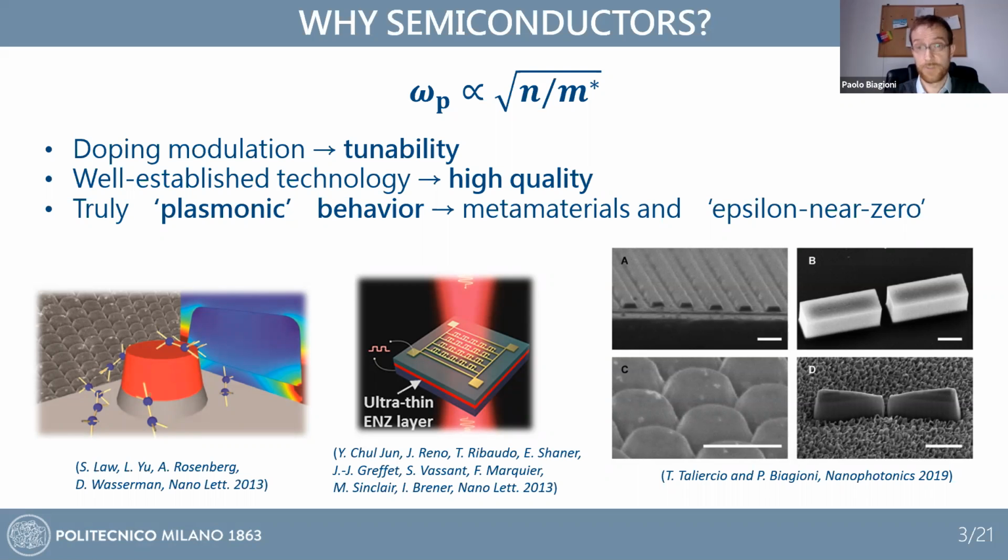Okay, the answer unfortunately is no, and is no by many orders of magnitude. There is no way that the carrier concentrations required in the mid-infrared can be sustained by CW excitation. It's technologically impossible, and you will destroy your material, even if you could reach those powers. So no, you need pulsed excitation, and of course, this is a thrilling opportunity in terms of devising active devices, ultra-fast active devices, but it has the strong technological limitation that it requires pulsed excitation for sure.